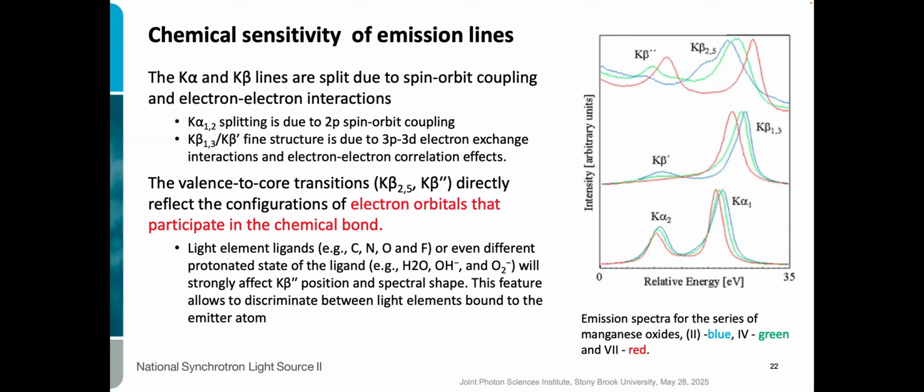All right, now this is a very powerful measurement. Why? If you think about core X-ray spectroscopy, it's not actually very smart to do it, because what you are after is chemistry, right? And chemistry happens in valence levels, very high in the energy. Whereas you're probing the core electrons, they're deep, very deep. They don't even interact very much. And still, there is the coupling that allows you to tell, oh, because this line shifted, even though it comes from the electron in the deep core, that tells you something about the oxidation state, which is the valence level proper. This is your microscope into the valence states.